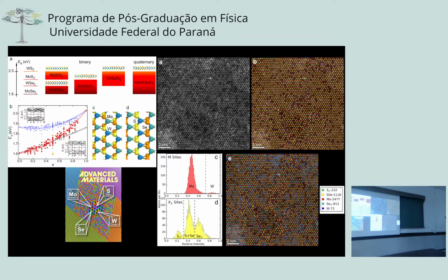I get a single band gap. Once I start mixing two, for example, if you have MoSe2, I start putting tungsten in it. What will happen? It's going to follow this line, linearly, generally, theoretically. So it's going to have a much bigger band gap. If I keep on doing it, if I can mix four different elements, moly, tungsten, sulfur, selenium, we can have the same 2D material. By changing the initial precursor, we can tune the band gap from 1.6 to 2, right?